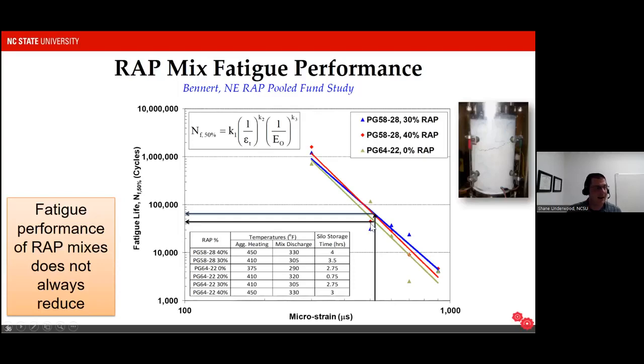And in their mix, the way they designed the mix happened to result in the higher RAP cases, on the mean, on the best fit of this function, being better. There is, of course, a lot of scatter, and so there's a lot of uncertainty. But unlike the North Carolina study, this study showed that RAP could be designed with better performance, or at least equivalent performance, to a non-RAP case.